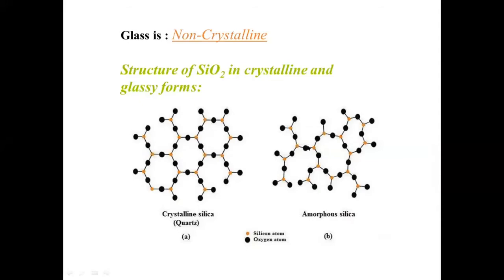So each silicon atom is bonded to 4 oxygen atoms. But here you see only 3 oxygen atoms because the 4th oxygen atom is out of the plane. It is along the perpendicular axis, perpendicular to the plane of this blackboard or the computer screen. So the coordination number of silicon with oxygen, coordination number meaning the number of nearest neighbors. How many neighbors are there for each silicon atom? The coordination number is 4 for silicon in the amorphous form as well as in the crystalline form.